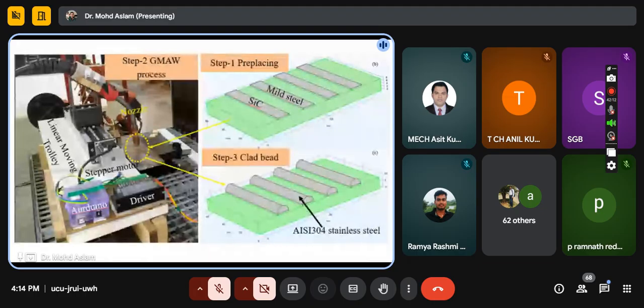First one, incomplete fusion at the end of the cladding. And in the case of steel, less dilution. That problem I solved with the help of MMC powder. I used silicon carbide. First of all, I placed the silicon carbide on the mild steel material. After that, we used wire arc additive manufacturing, gas metal arc based wire arc additive manufacturing. In this case, we used an AISI 304 stainless steel electrode, which developed a cladding layer on the substrate.